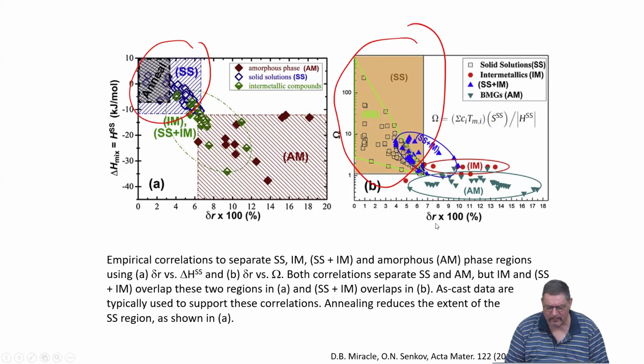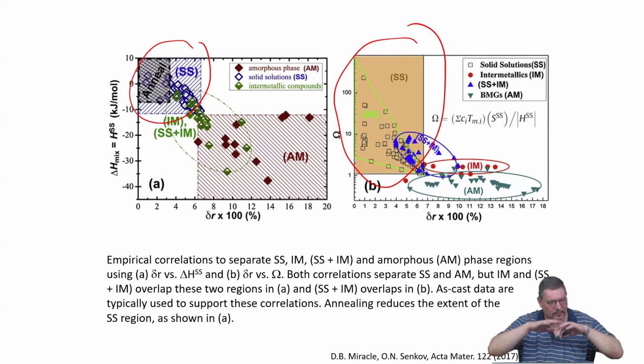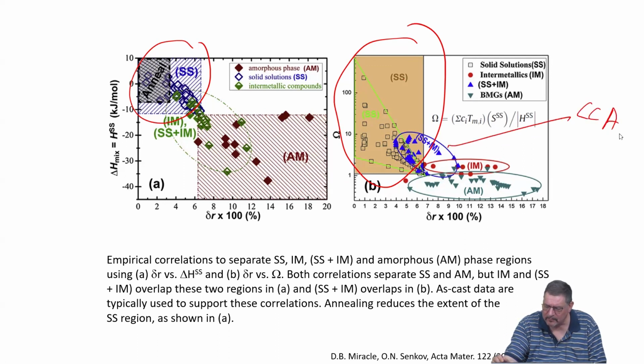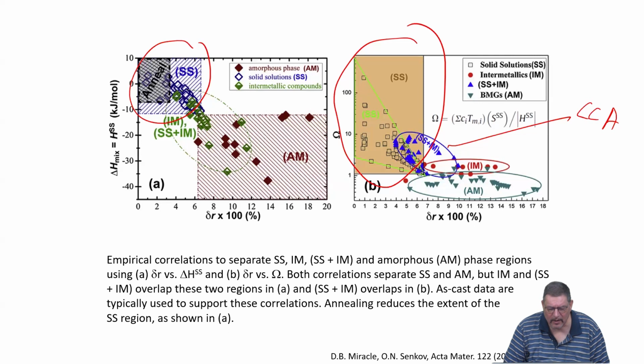So it's basically the similar concepts, and you see that specifically this omega parameter as a function of lattice distortion sometimes it's called, but it's more like the variance of atomic radii inside the solid solution works fairly well, because you have a nice separation between the regions where crystalline solid solution would form, or where amorphous materials form, or where you have intermetallics, or where you have CCAs in this two-phase region. So this, I think, are good. This is the omega parameter, you know, which combines. No problem. Good to ask always.